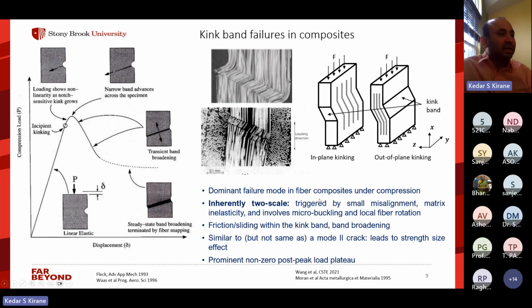Another point is that it can happen in various directions depending on the properties of the matrix. It can be in plane, shown like this. So the kinking is in plane or out of plane. A lot of observations suggest that if your loading angle is small, the preferred mode is out of plane, and then at higher angles of loading with respect to the fiber, you can observe in plane kinking.